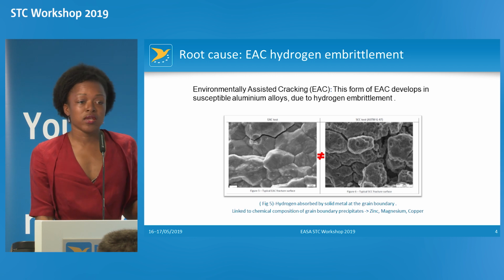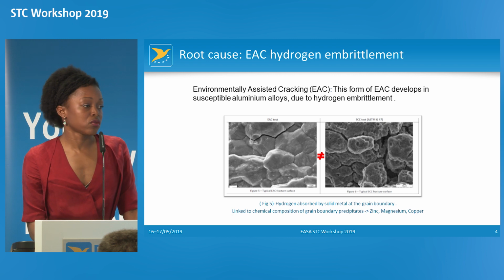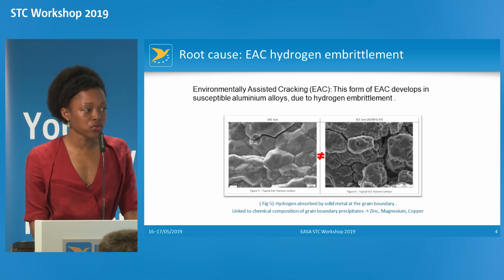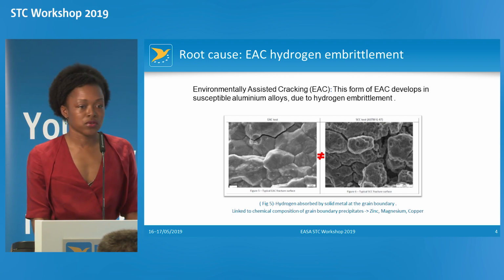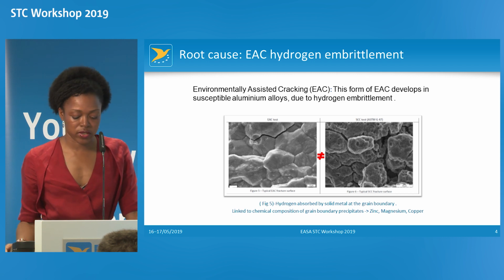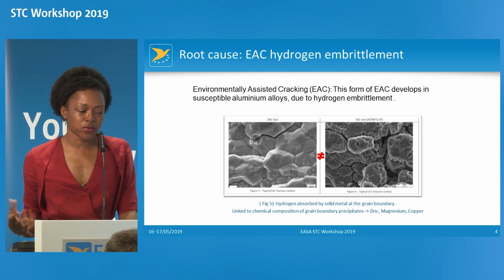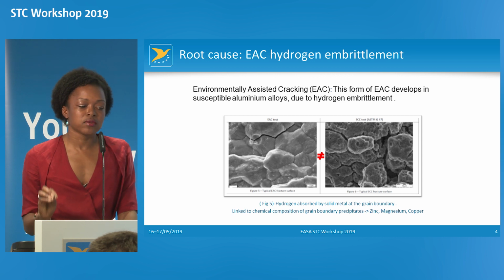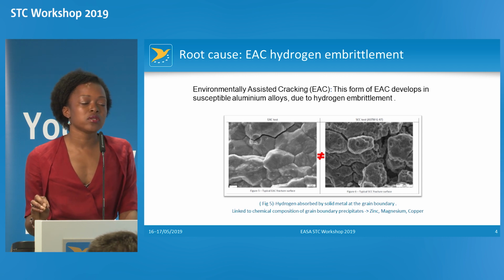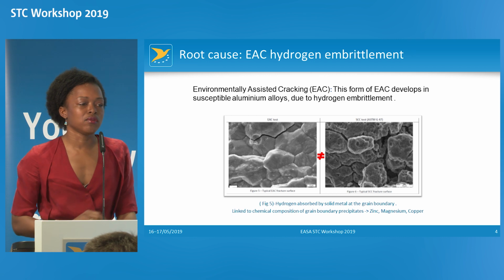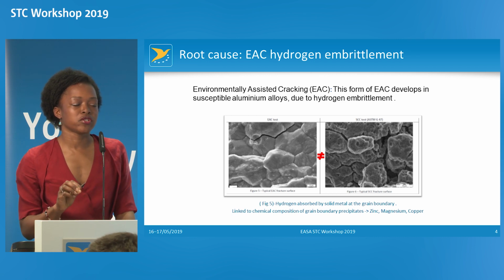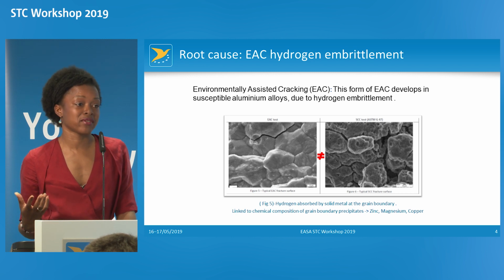Today, in the airplane industry, we usually use stress corrosion standards to evaluate EAC. The conventional standard is ASTM G47, and this is done in a very severe, salty atmosphere. This standard didn't exhibit the kind of environmentally assisted cracking generated by hydrogen embrittlement. Actually, it tends to mask it.